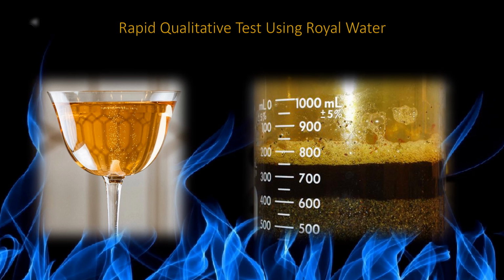A white residue at the bottom of the beaker will likely be silica, that is, quartz. By weighing it, the percentage may be calculated. If there are other residues associated that may be dark red-brown or black, these could be iron oxides such as magnetite or hematite. They may also be sphalerite or galena, which are sulfide complexes. After decanting, washing, filtering, and drying, the magnetite itself may be removed with a magnet, confirming the mineral.